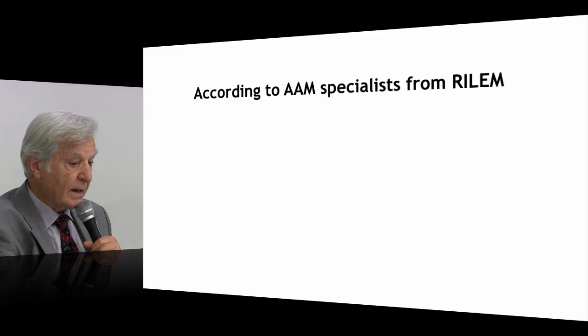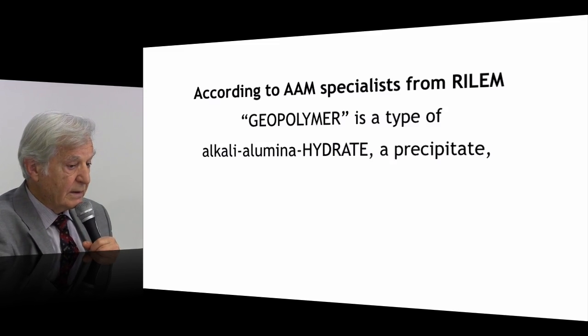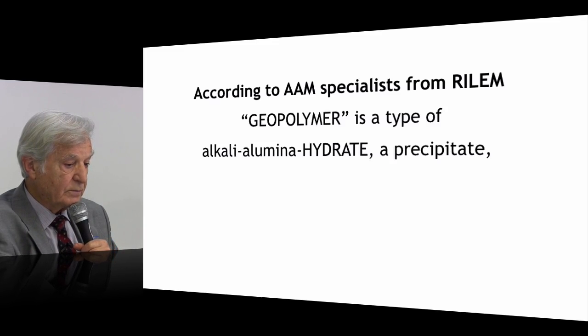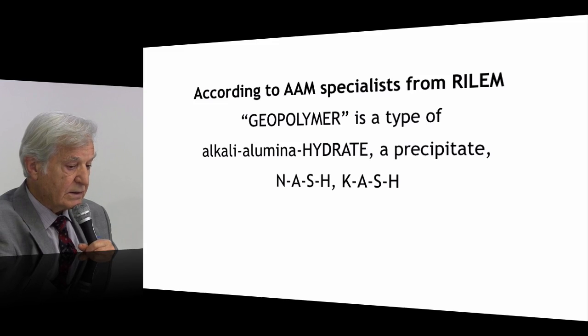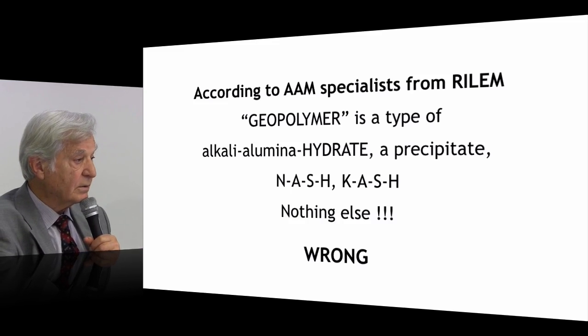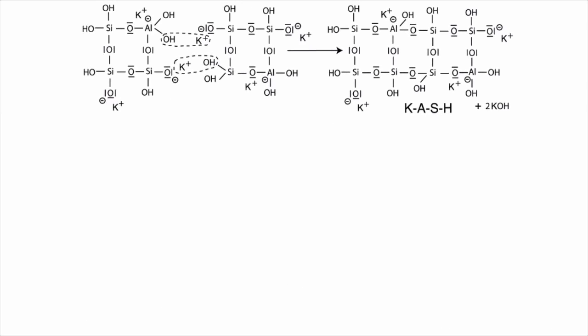So according to alkali activated materials cement scientists, geopolymer is a type of alkali aluminohydrate, NASH, KASH, nothing else. It is wrong. Geopolymer results from polycondensation of well-defined monomers, like this one, Si-Al 3-1. This is the polysialate disiloxo cycle that polycondenses and builds the first ribbon. Oligomer, it is a small molecule that can be called KASH. You have the potassium, you have the hydroxyls, and you have some water, and you have the KOH.